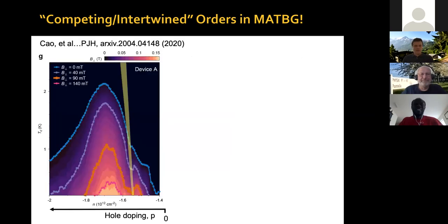So now you can actually do this continuously. You can measure TC. These are measurements of TC versus hole doping at different magnetic fields, and the magnetic field is varying continuously. Here I'm showing just particular traces at different values. And what you can see is that at some finite magnetic field, you split the superconducting dome into two domes. Then you suppress the smaller part, and you remain with only one dome.